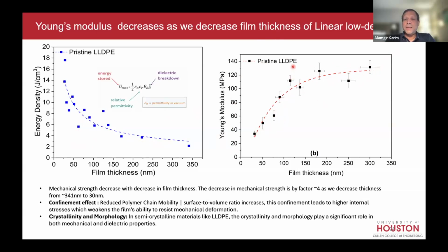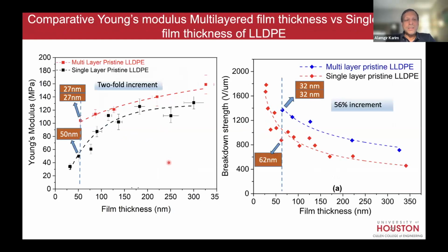So there's probably too little crystallinity to orient and align as you decrease film thickness in LLDPE. So it behaves like the other systems we have studied. Anyway, the point is that these are not correlated. Mechanical property does not seem that much correlated to the energy density storage. We think it's related to free volume and chain packing, chain orientation and packing, and confined film thickness. So this is more or less, one last thing.